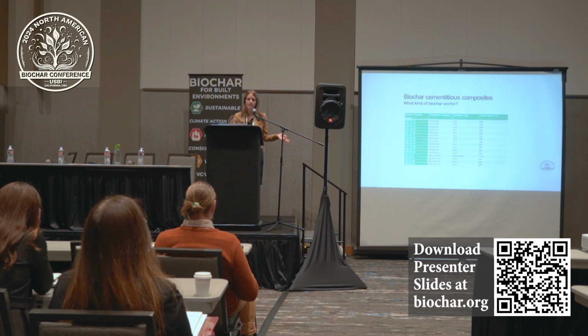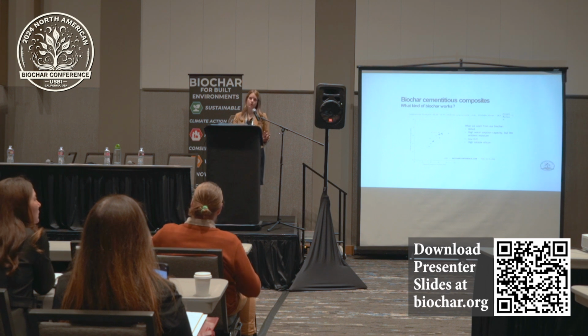However, as you saw with the strength data, not all biochar is created equally. I mean, it seems like some of the biochar does improve strength more than some of the other biochars. And this is important because feasibly that means that we could replace even more of the cement with those types of biochar. So what's important? We've done a pretty thorough statistical analysis and found that there are 3 variables that we really want to control in our biochar. And those are ambient saturation percentage, I'll explain that more in a moment, soluble silicon, and our oxygen to carbon ratio. I'm realizing this PDF transformation did not work well, so I apologize for that.